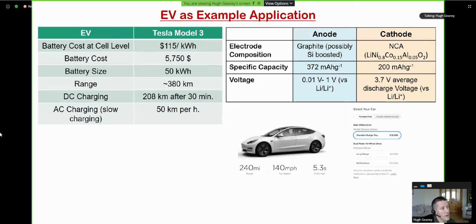So cathodes are slightly broader in that they'll tend to be a lithiated metal oxide material. So this is a nickel cobalt aluminium oxide. And you can see that the stoichiometry is 0.8 in terms of nickel, so it's quite a nickel-rich composition. In terms of capacity, it's about 200 milliamp hours per gram, which you see is below the capacity of the anode, which means that it's the limiting electrode in terms of the overall battery. The voltage is also very important here. The voltage for NCA is about 3.7 volts as your average discharge voltage.